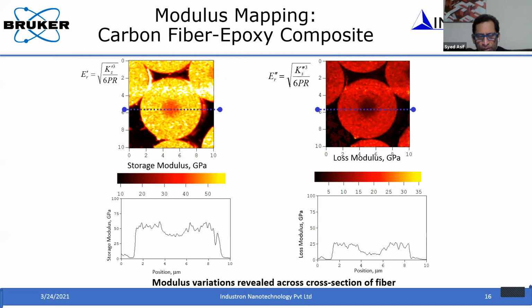If you have to do these experiments one indent at a time, even at one indent per minute, it will probably take about 30 to 40 days. Whereas with this mapping technique, you can get this property map within about 5 to 10 minutes, by not only doing the experiment, but also analyzing the data.